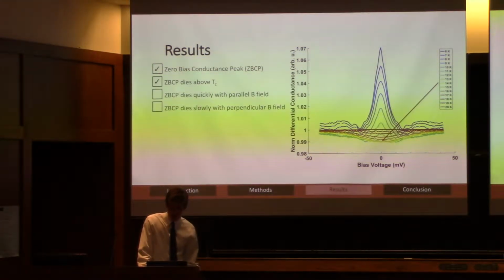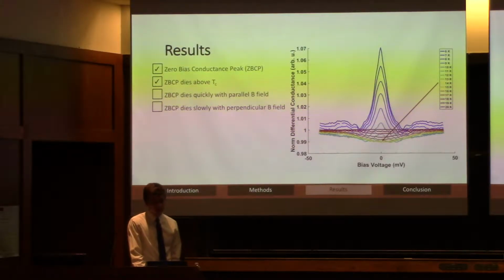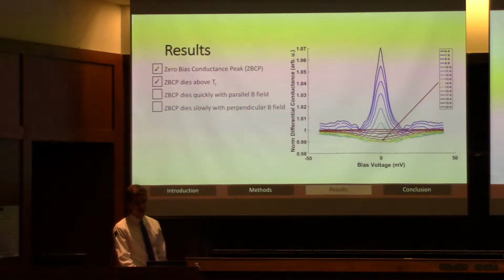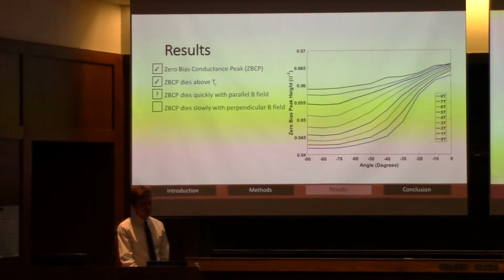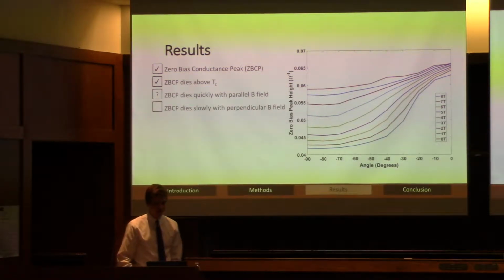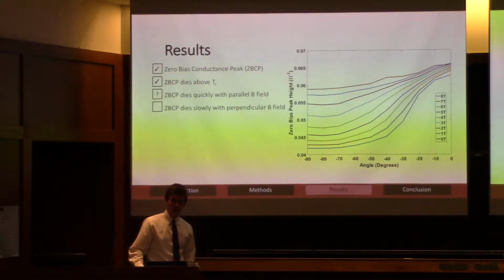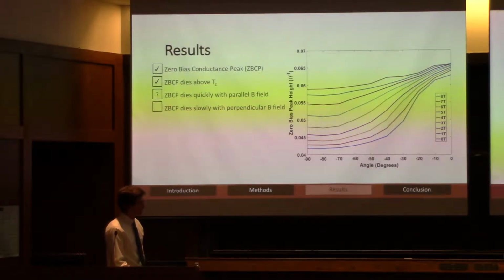And according to that Doppler effect, we also want to see that this peak dies quickly in a parallel field configuration and slowly in a perpendicular one. And it turns out that is the exact opposite of what we see. So this is a plot of the height of that peak as a function of angle with respect to that magnetic field. Each one of these colored lines is a magnetic field value. We went up from 0 Tesla to 8 Tesla.